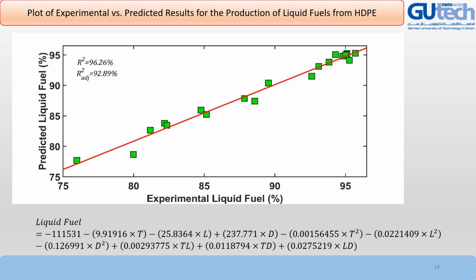The result of experimental analysis and experimental design analysis is shown in this plot. The plot shows experimental versus predicted results for the production of liquid fuels from HDPE, and the model which has been produced from the experimental design using CCD is shown in this slide. As you see, the R square value is very good. It's 96.26, and adjusted R square is 92.89, which shows the higher accuracy of the model.